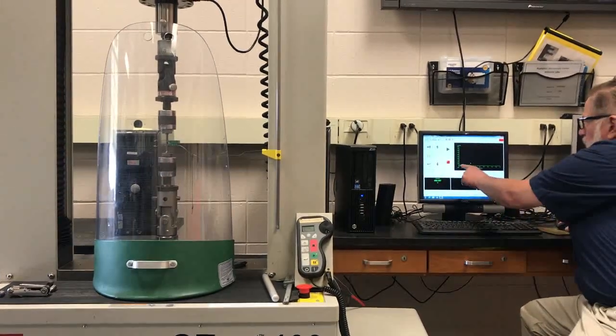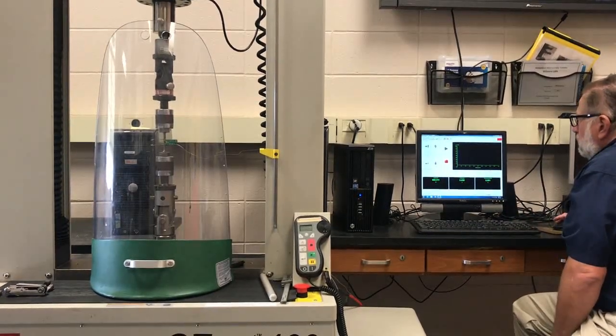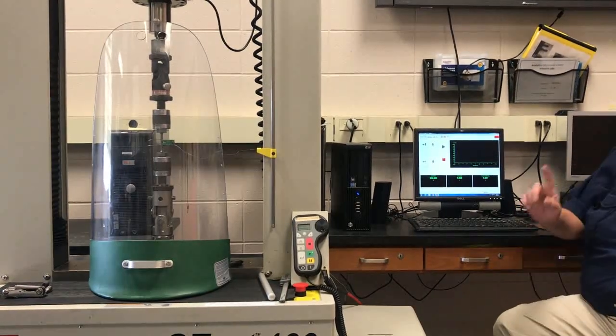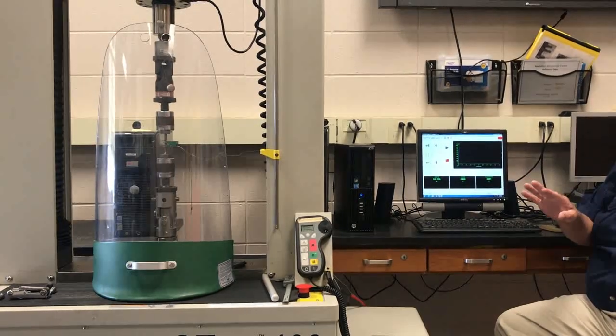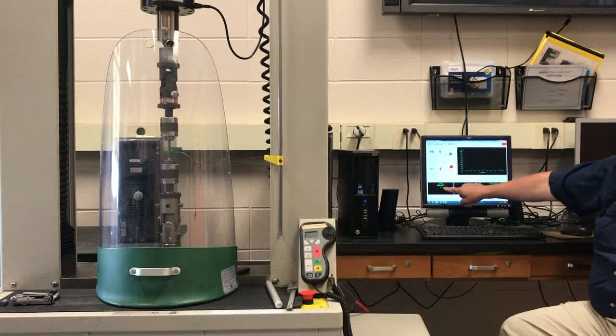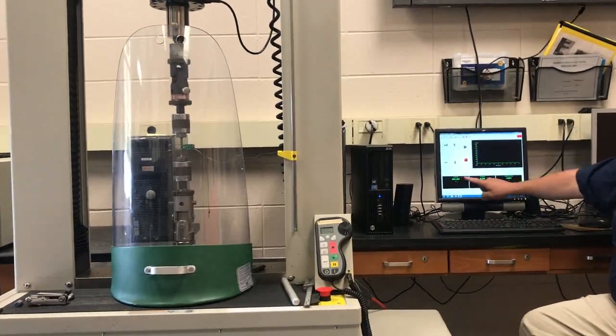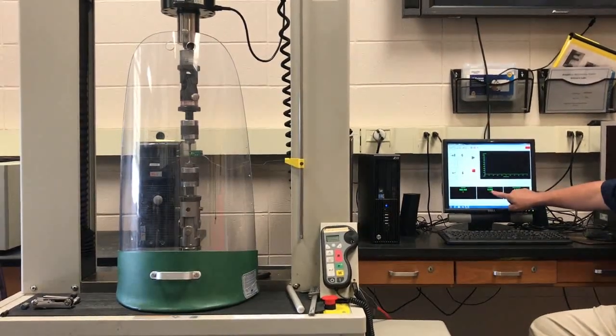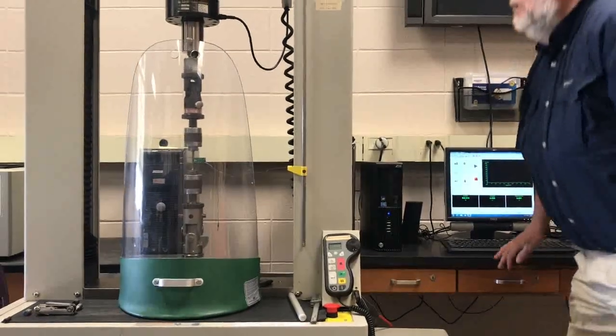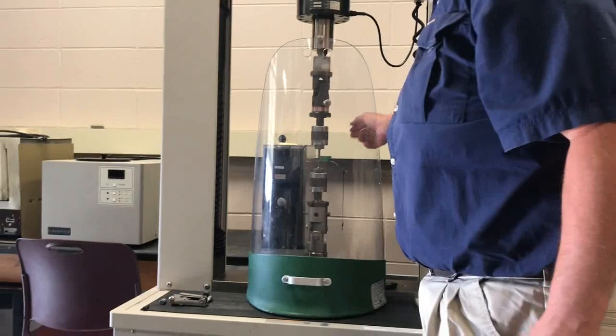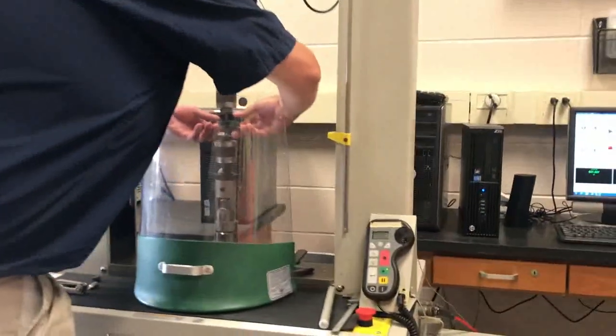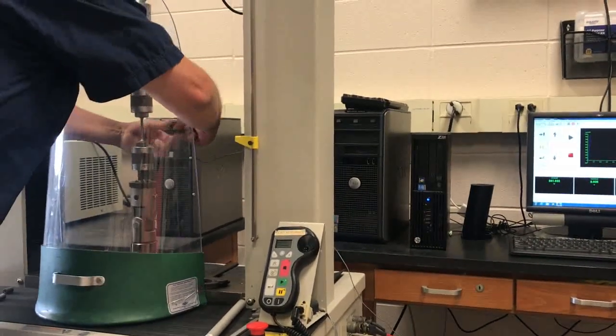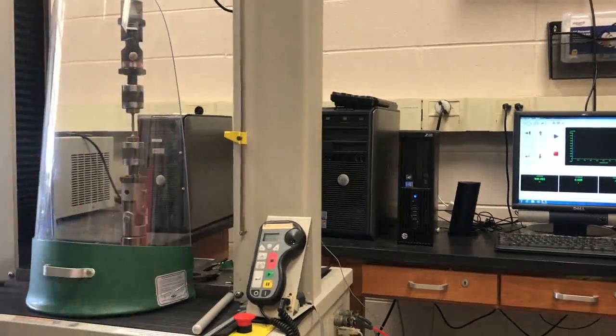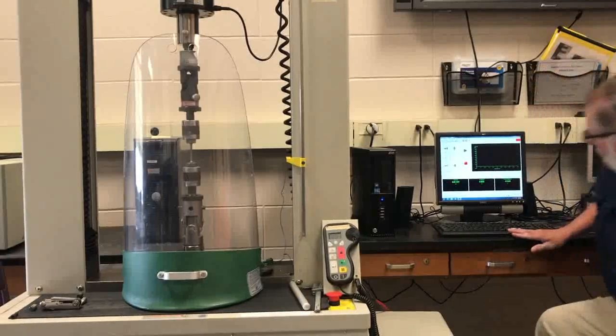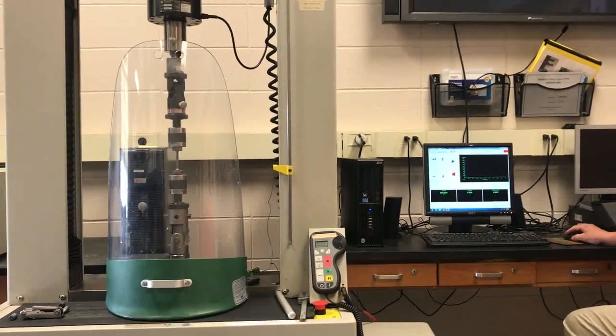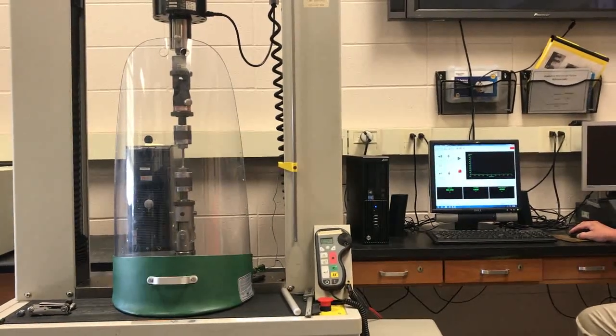You may be able to see there's a blue linear line here, and I'm going to pause it before it gets to the yield point. And for the sake of preserving the integrity of the extensometer, I'm going to go ahead and remove it carefully. Notice that we're already at almost 1,000 pounds force. Crosshead has moved approximately 35 thousandths of an inch, and the extensometer reading is here. Remaining behind the shield, reach around and remove the extensometer carefully from the sample and place it on the stand, and come back to the computer and press pause to continue the test.